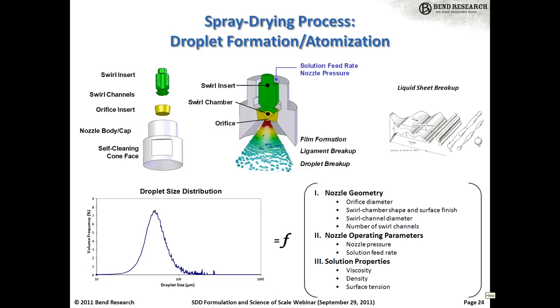And the droplet size is very difficult to model from first principles, since as the liquid exits the nozzle orifice here, it forms a liquid sheet that breaks up into ligaments and then finally into droplets. And this whole process is heavily influenced by things like turbulence, which is just inherently very difficult to model. But there is quite a bit of literature data out there relating the droplet size to these parameters, particularly in the automotive industry. They tend to use quite a bit of these pressure swirl nozzles.